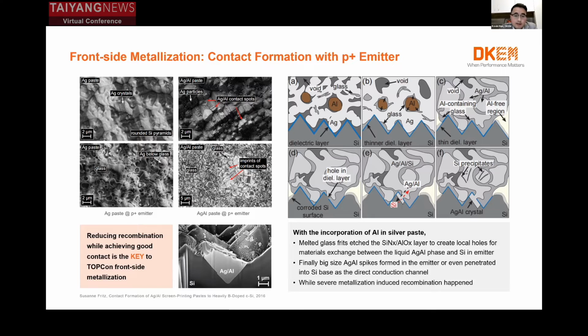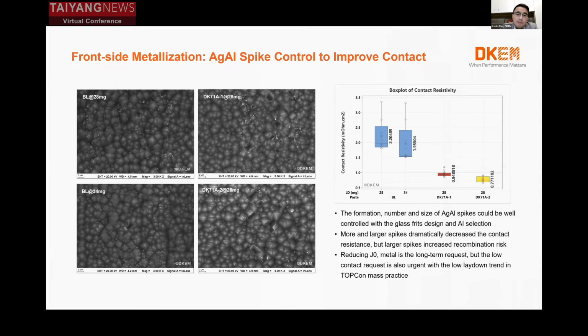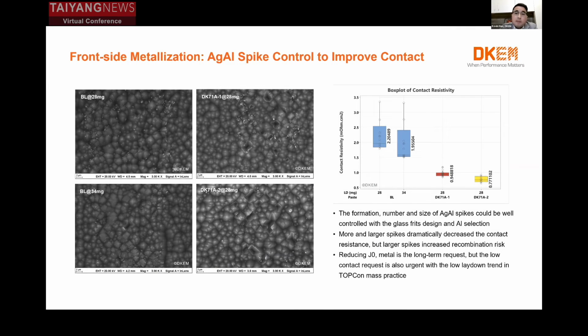Unfortunately, such big size spikes will cause severe metallization recombination. So it's very important for us as paste suppliers to reduce recombination while achieving good contact. This is quite important for the TOPCon front side metallization. So how can we control this kind of spikes to get a balance between the contact and the recombination? First, we would like to talk about how to control spikes to achieve good contact.